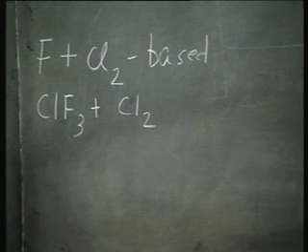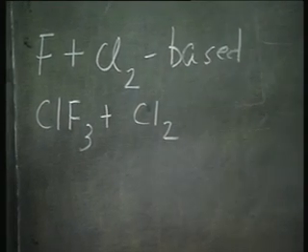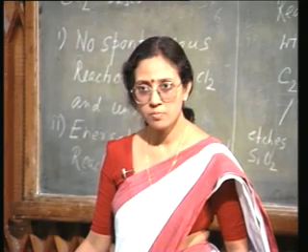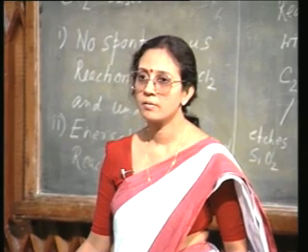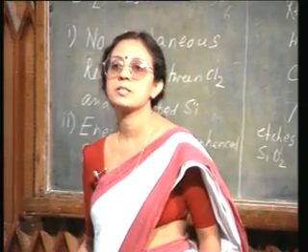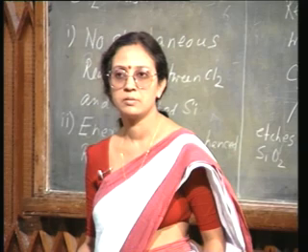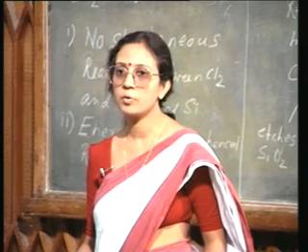What you have is, you start with pure ClF3. So, pure ClF3 is going to give you mostly fluorine, okay? Mostly the active species obtained in a ClF3 plasma is going to be fluorine. So, the etch profile will be isotropic. Fluorine based etching, I am going to have isotropic profile. You start increasing the percentage of chlorine slowly. What will happen? Slowly the anisotropy in the profile will start increasing, right?